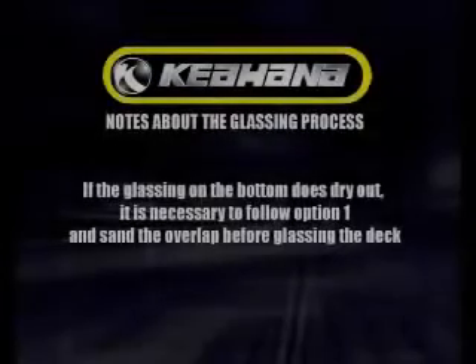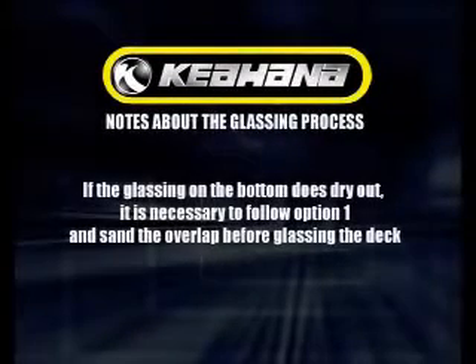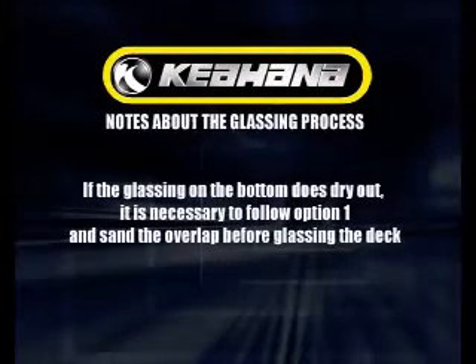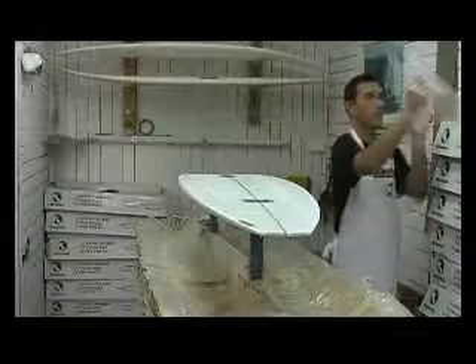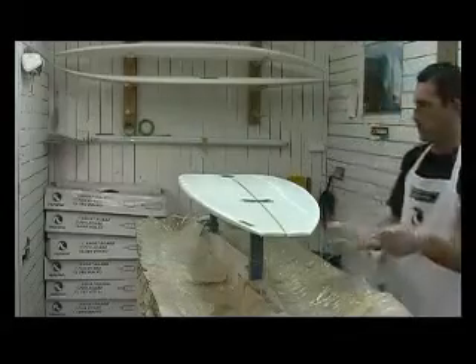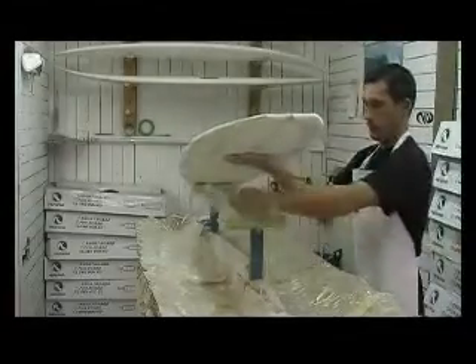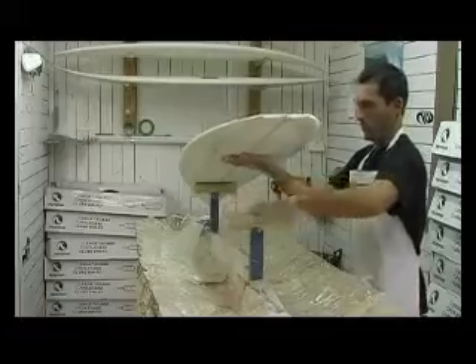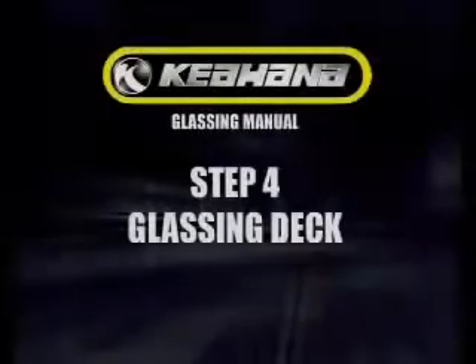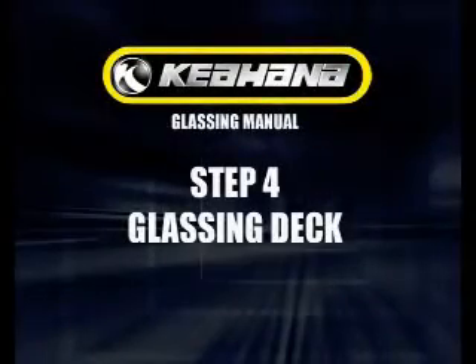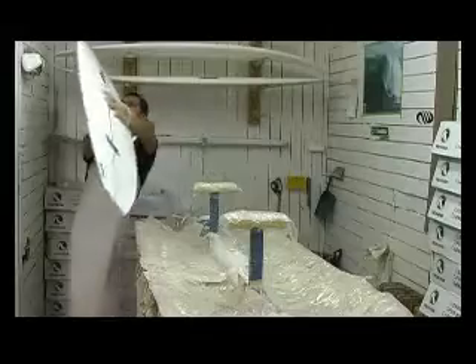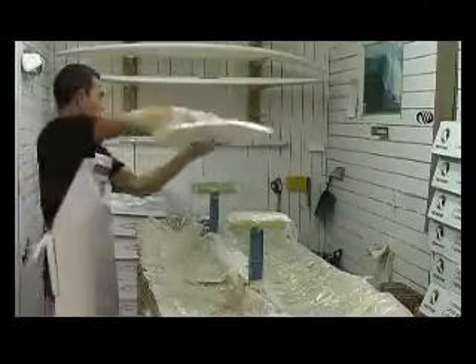If the glassing on the bottom does dry out, it is necessary to follow option 1 and sand the overlap before glassing the deck to create a proper bond between the dry resin of the bottom and the wet resin of the deck. Wrap some plastic around the stand to prevent the bottom resin from sticking to the stand when glassing the deck. Glassing deck. Turn the board onto the deck.